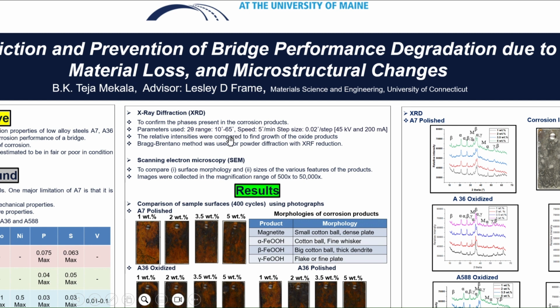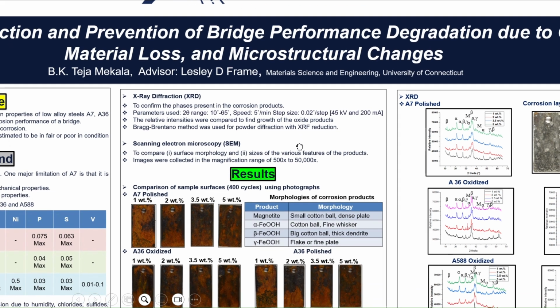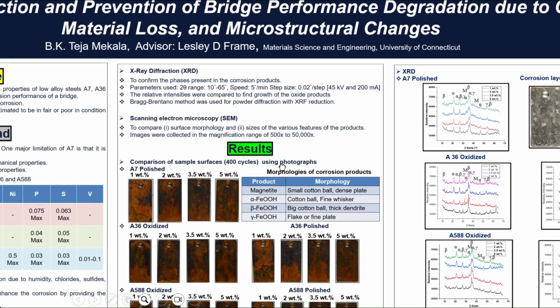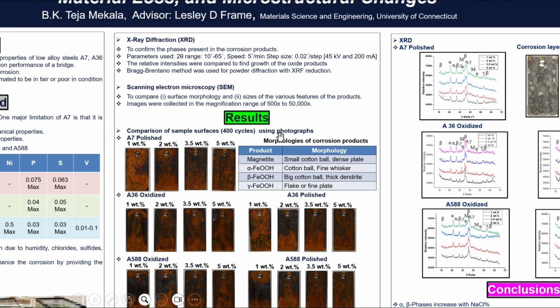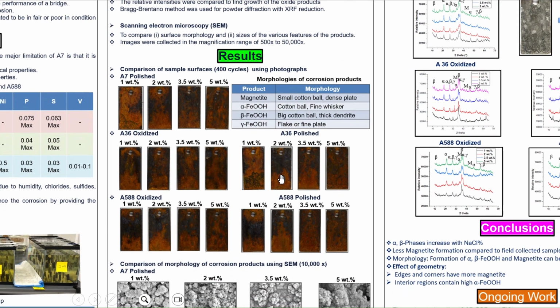products, and the parameters used are mentioned here: a 2 theta range of 10 degrees to 65 degrees, a speed of 5 degrees per minute, with a step size of 0.02 degrees per step. The Bragg-Brentano method was used for the powders, with the XRF reduction mode. Scanning electron microscopy is also used for surface morphology study and to compare the sizes of various features of the products. Now, I would like to talk about the results.